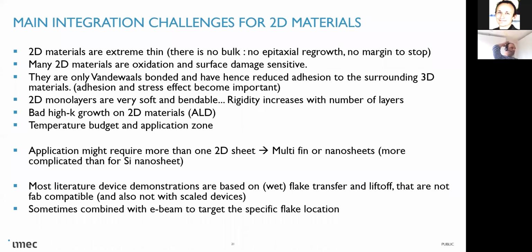But there are also a lot of integration challenges. One of the first ones is that 2D materials, this is very obvious, are extremely thin. So there is no bulk. Once you have touched or destroyed the material, there is no way to heal it through an anneal or whatever, because you can have no epitaxial regrowth, and there is no margin to stop. So if you want to do an etch or touch the material, you always need to be very careful that you do not destroy it.